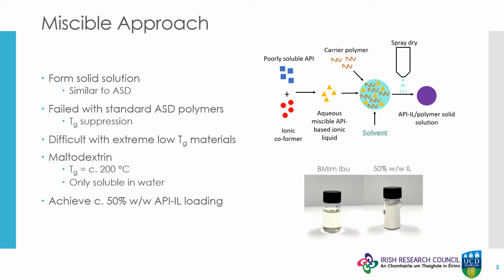The polymer found most suitable for this was maltodextrin, and we were able to successfully form a solid solution of the two components at a benchmark value of 50% weight-for-weight ionic liquid, with the recovered content being a fine white powder. However, even at marginally higher loadings, the glass transition temperature suppression becomes too substantial to recover a solid product. Unfortunately, our ability to work around this using lower processing temperatures is severely limited by maltodextrin's extremely low solubility in even small amounts of organic solvents.